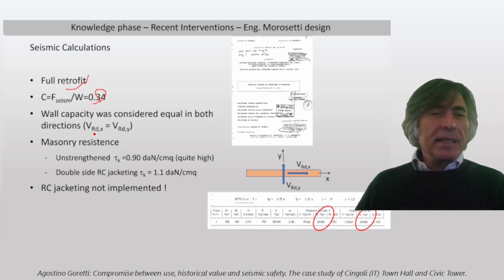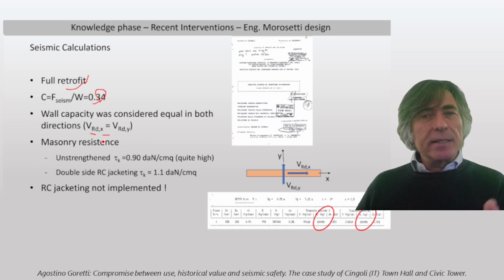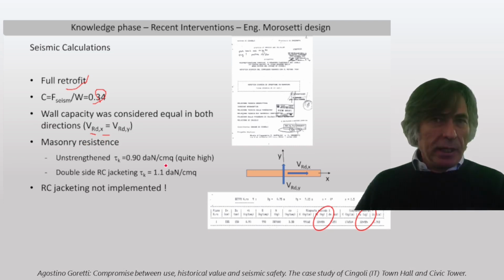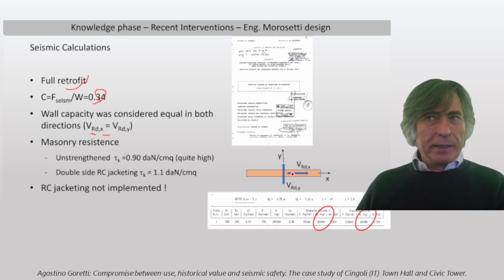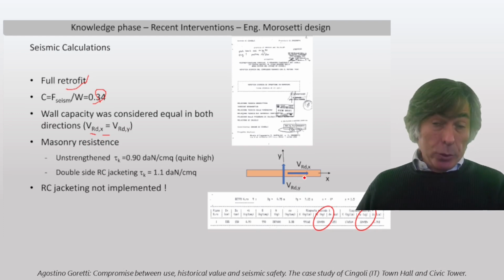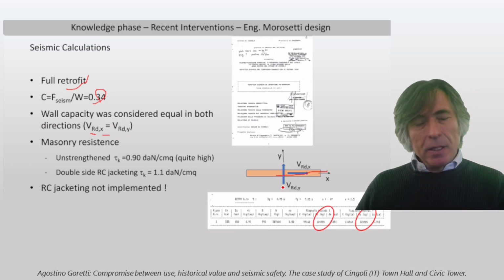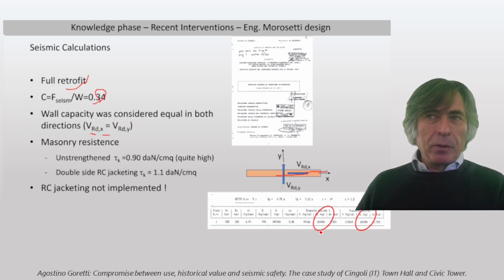First of all, the same shear resistance is adopted in both directions, in the longitudinal and transversal direction of the walls, while usually we consider only the longitudinal direction. In the transversal direction, the wall is assumed as not resistant. This can be seen from the output of the calculation. In the x and y direction, the resistance is the same.